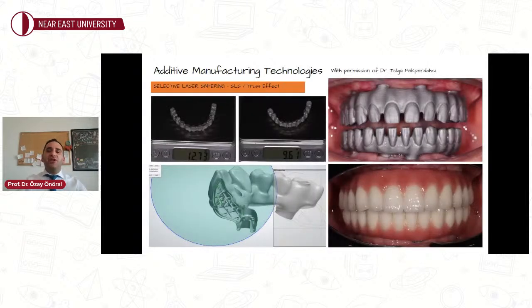I want to extend my appreciation to Dr. Tolga Pekperdachi for sharing this case with me. He investigated this issue that I mentioned in the last slide, and he checked the weights of these frameworks with the SLS technology. However, in one of the frameworks, a hollow design with the truss effect was performed, and please check out on the side the weights of these two frameworks. Both are SLS fabricated. The main difference is that one is hollow, fabricated with the truss effect, and the other one is with full density.